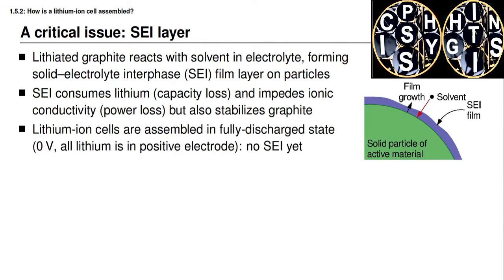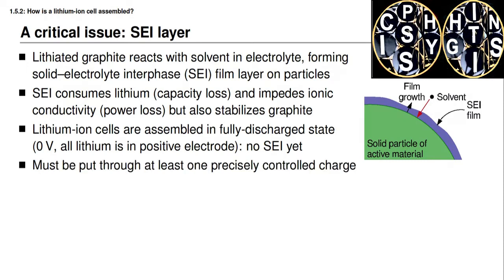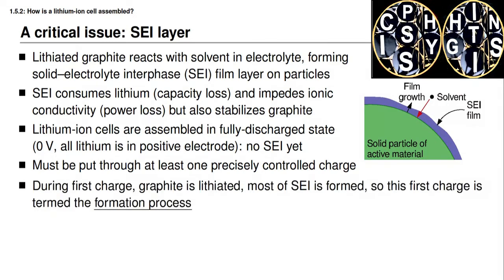When the lithium-ion battery cells are assembled, they are done so in a fully discharged state at 0 volts. All of the lithium begins in the positive electrode. The negative electrode is pure graphite with no lithium in it whatsoever. So at the beginning point of the manufacturing process, no SEI has formed. But when we build this battery cell, we must put it through at least one precisely controlled charging process. And during this first charging process, the graphite is lithiated for the first time, and this causes this chemical reaction that forms the SEI layer. And because of this formation of an SEI layer, the first charging process is called the formation process.